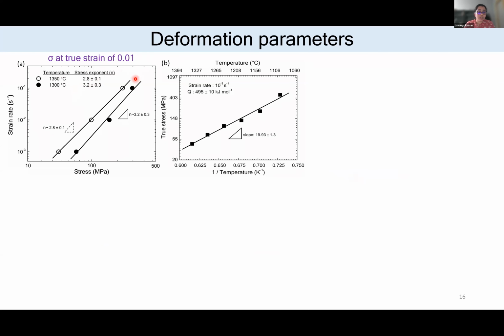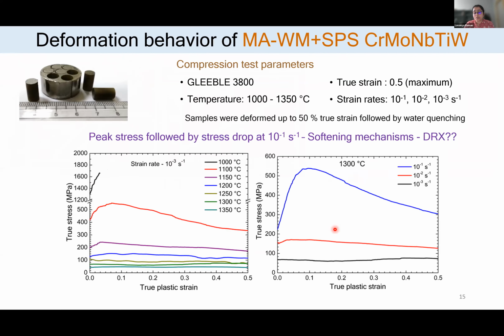So generally, if we do that at 1% strain, we have a stress exponent of 3 and an activation energy of something close to 500. But here we have seen that the material is very sensitive to the way we deform, whether it is in a fast or in a slow way. So the material is very sensitive to the strain rates. So what we tried to do was calculate these parameters as a function of strain and strain rate.